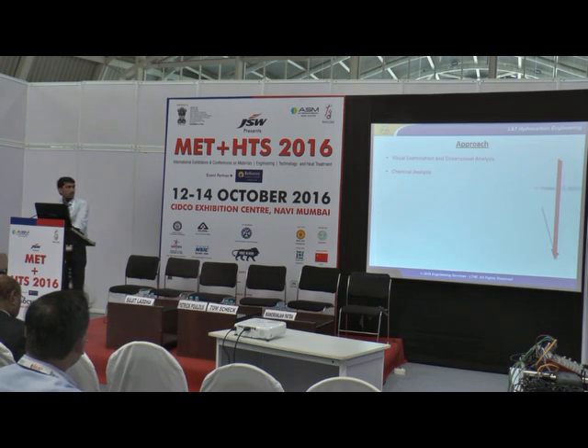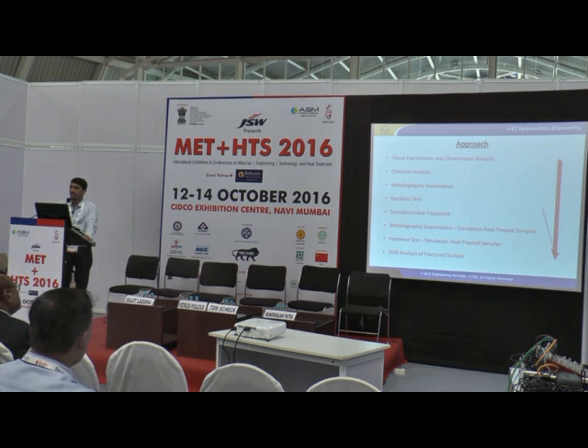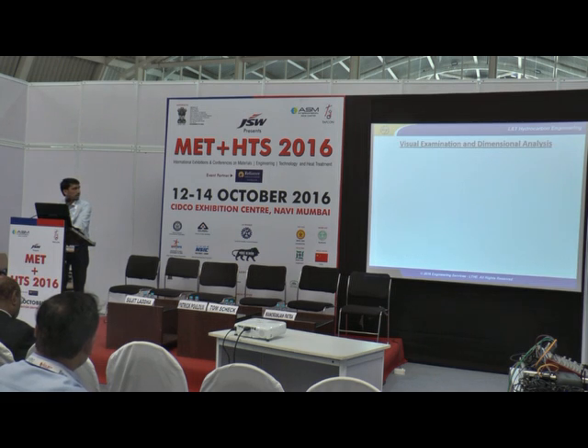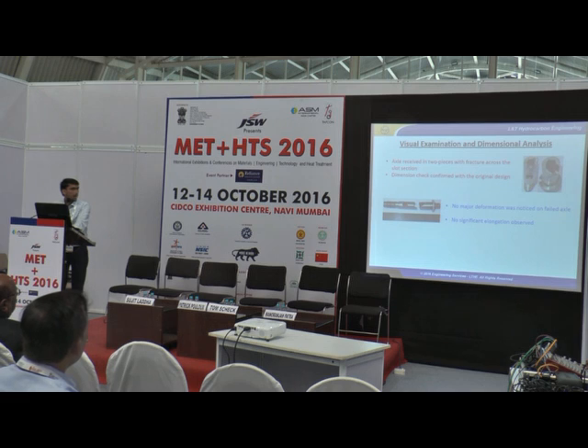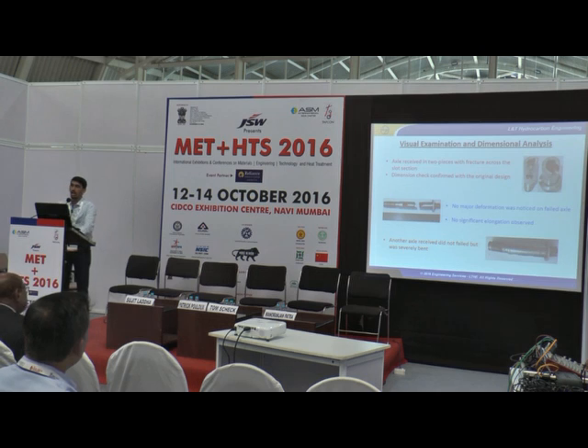The approach of the investigation was in the sequence seen in the slide. Visual examination, followed by chemical analysis, metallographic examination, hardness test, simulation heat treatment that we carried out in the lab, then again metallographic and hardness tests of those simulated samples, and finally the SEM analysis of the fractured surface. Visual examination confirmed that there was no deformation, and the dimensions checked in the as-received condition were conforming to the design specifications, but the axle was received in two fractured components. No major deformation was seen and no significant elongation was observed on the component. Whereas the third image here is another axle that we received in a bent condition, not fractured but bent.